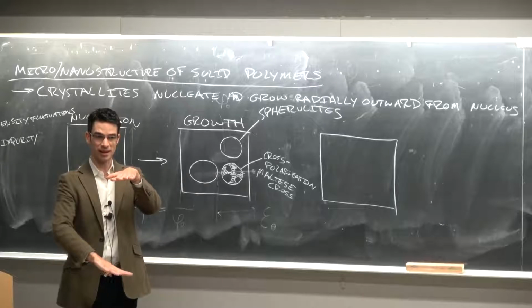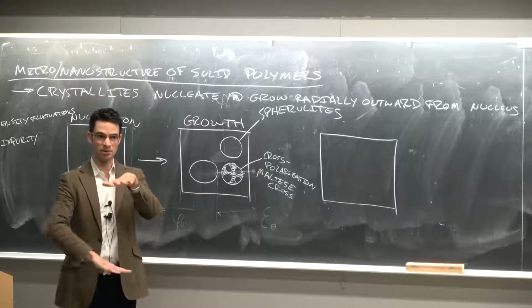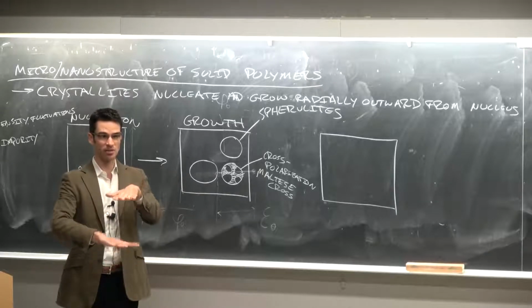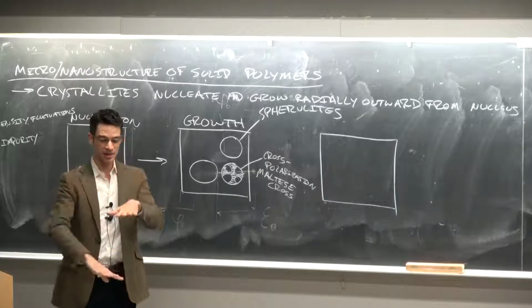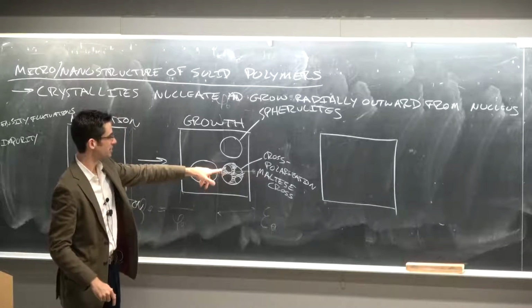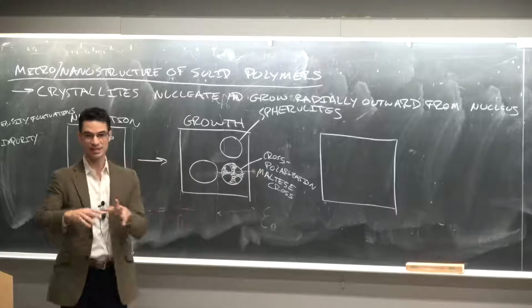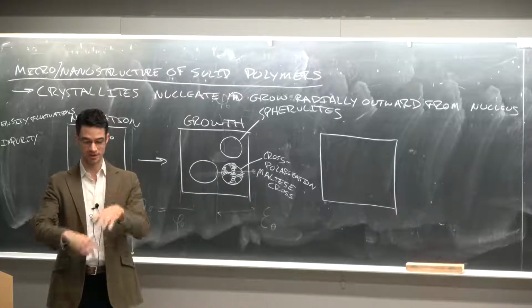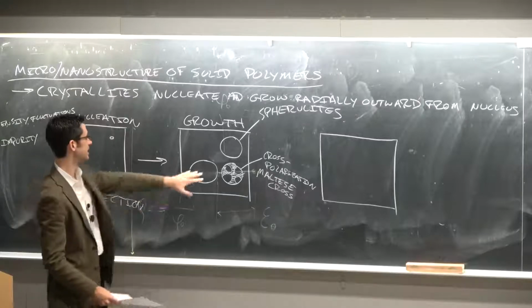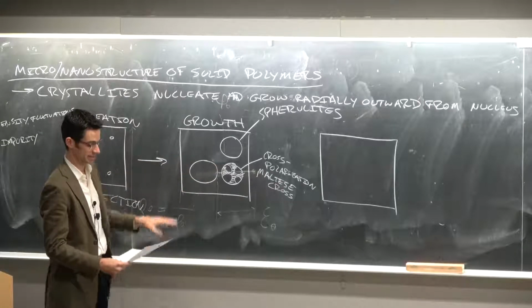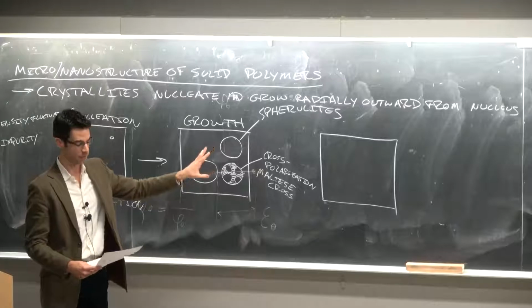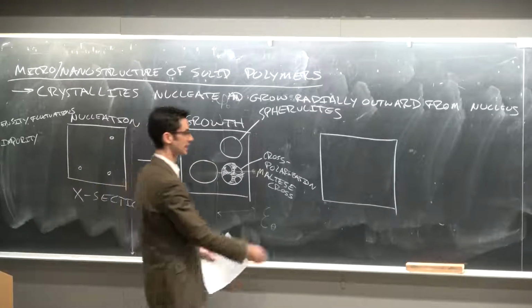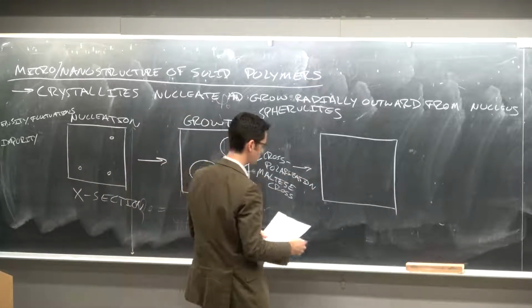Now, ordinarily, when light comes through with no sample in between, just like in an LCD display, all the light would be blocked and you'd see nothing. But because these oriented polymer fibers within the spherulite rotate light, in certain regions you get this cross pattern developed, and that's indicative of crystallization, and we'll look into what exactly this microstructure is in just a minute.